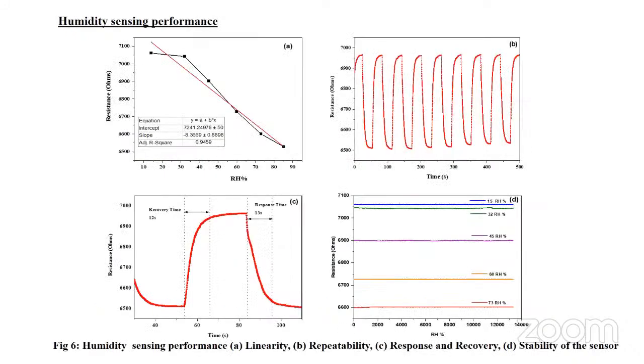The fabricated sensor has good humidity sensing performance. In the first graph, the sensor showed a good linear relationship between the resistance and the relative humidity. Then the absorption and the desorption processes were repeated for several cycles, and it indicated the excellent repeatability of the sensor. In the third graph, the fabricated sensor showed a good response time and recovery time, which were 13 seconds and 12 seconds.